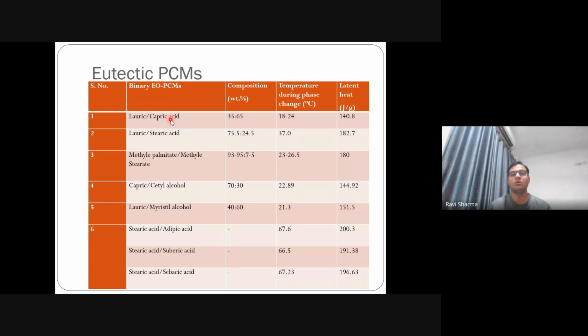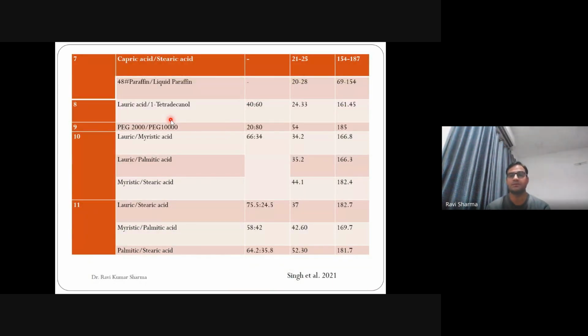So what we will do, we'll mix two materials. One is of 40 degrees centigrade, one is of 45 degrees centigrade. We will mix them in a different ratio until we find a material with a melting point of 42.5. So that's how we prepare the eutectic. It can be binary, it can be ternary, or it can be more, depending on the material availability and the requirement.